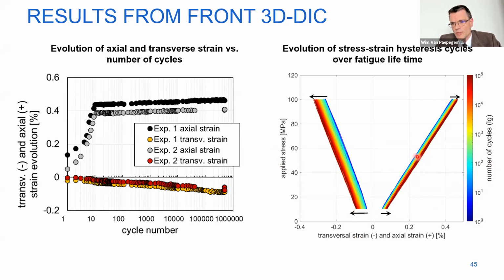And you see that the hysteresis loops shift from left to right, and here from right to left for transverse strain. So we have many data points for an individual cycle, so you can really measure the energy loss in one cycle and also look at permanent deformation over time. That was the frontal DIC.